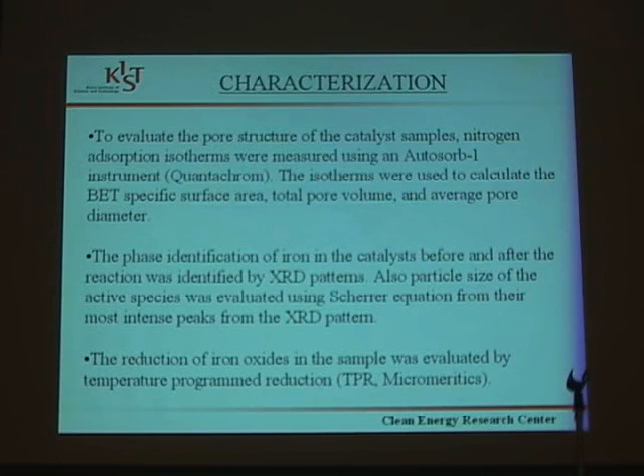We have carried out the evaluation of the catalyst for the pore structure using nitrogen adsorption isotherms, using the AutoSorb 1 instrument. The isotherms were used to calculate the BET surface area, total pore volume, and average pore diameter. The phase identification of iron in the catalyst before and after the reaction was done by XRD patterns. Also, the particle size of the active species was evaluated using the Scherrer equation from the most intense peak of the XRD pattern. The reduction of iron oxides in the sample was evaluated by the temperature programmed reduction method.